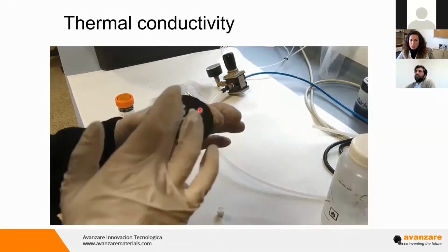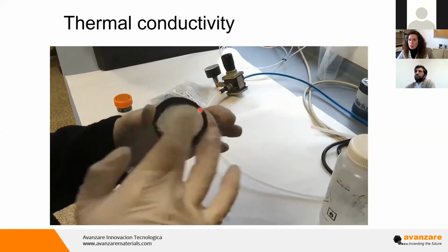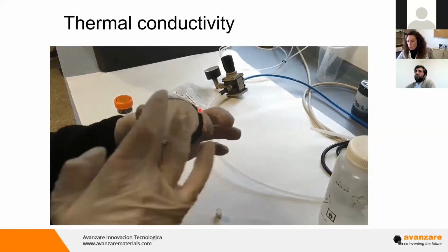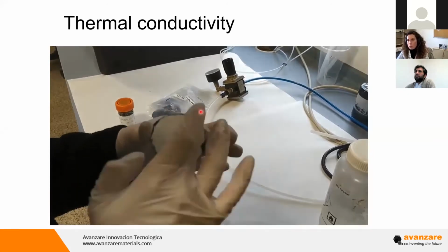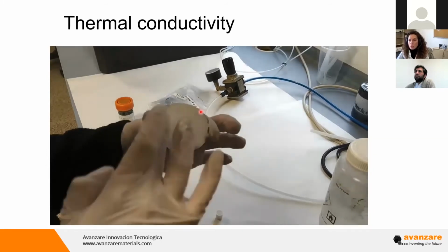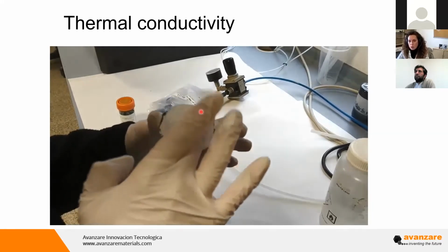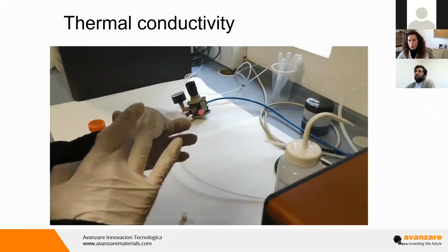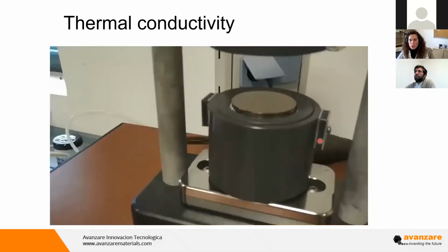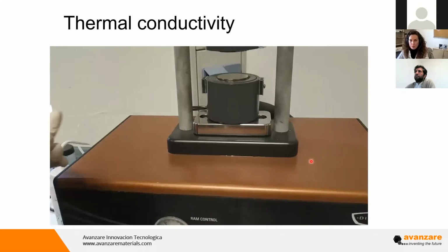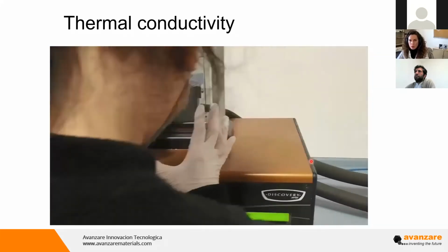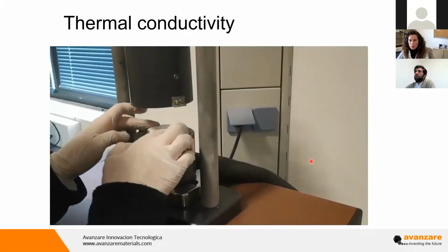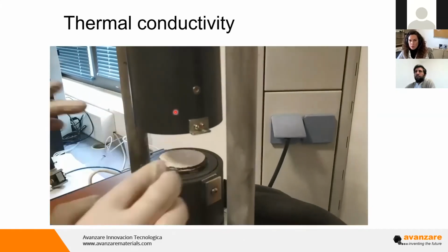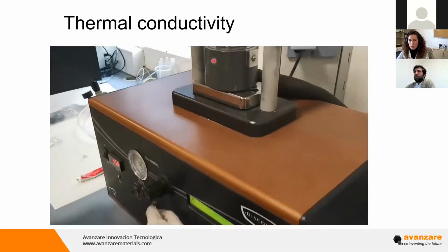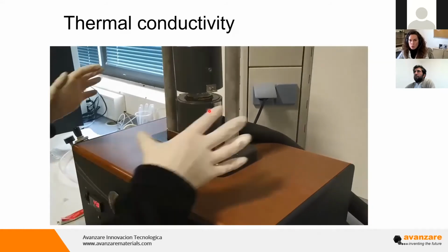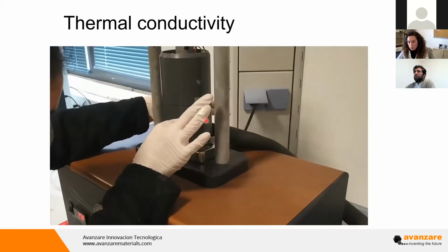Once it is inserted, the cell is perfectly closed to avoid any loss of heat, and after 20-30 minutes, the equilibrium is reached and the voltage, and so the temperature, of the upper and lower plate is recorded, as you see here. So now it's placed. Remember that this is the hot plate, the down one is the cold plate. We close with some pressure and it's perfectly closed.